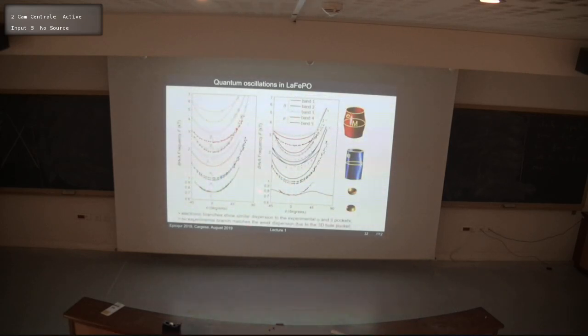And when you put all this information together, here are different frequencies, similar to what I just showed you, as a function of the angle between the normal to the plane and magnetic field. Then you notice this dispersion. So they are all quasi-two-dimensional dispersions for the different bands. And this is where we need band structure calculations to help us work out what they might mean.